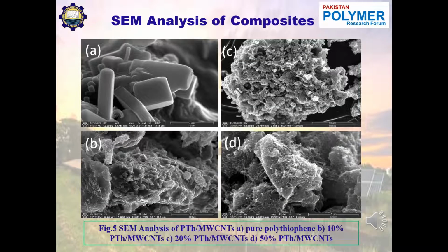The scanning electron microscopy characterization was done to study the structure and diffusion of synthesized nanocomposite. The images obtained via SEM showed dispersion of MWCNTs in polythiophene and the structure of nanocomposite obtained from the in situ polymerization. First of all, figure A shows the structure of pure polythiophene where the lumpy rectangular structure of thiophene is formed, whereas the disintegration of polythiophene can also be seen.